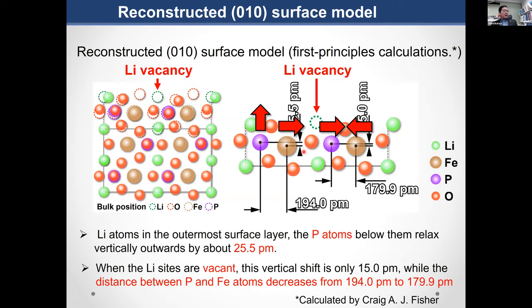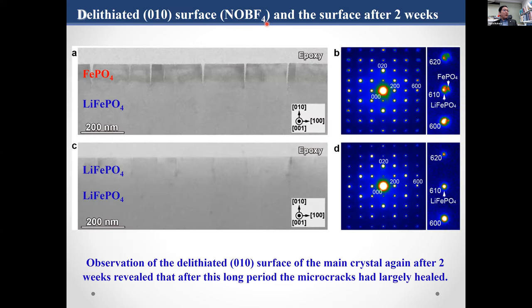And we then delithiated from the surface. Lithium is extracted by using NOBF4 liquid. So lithium is dissociated from the LiFePO4. Therefore, FePO4 is produced. Because the mismatch between FePO4 and LiFePO4 is different, cracking occurs like that. So the diffraction pattern obtained from here also indicates two phases coexisted.